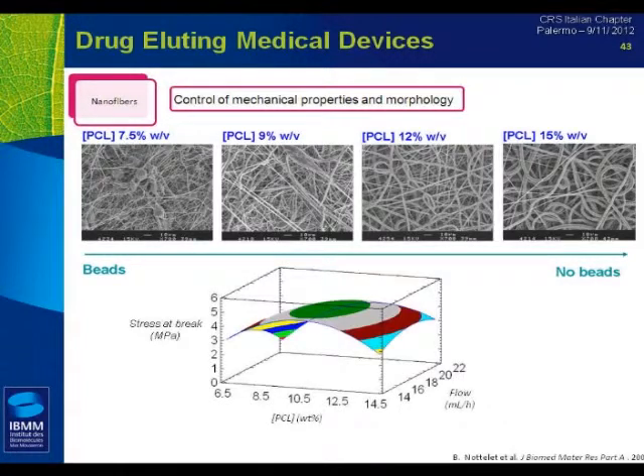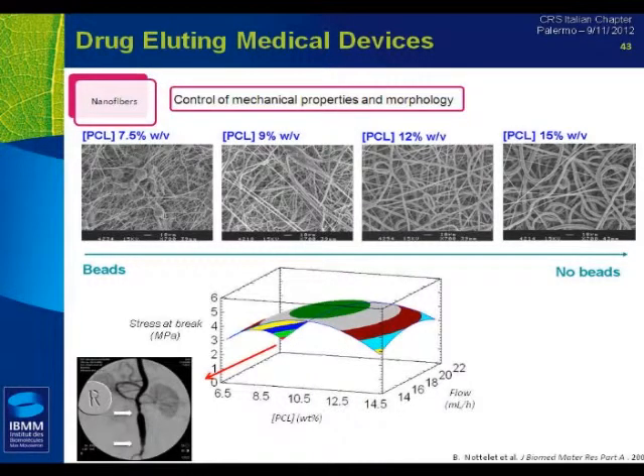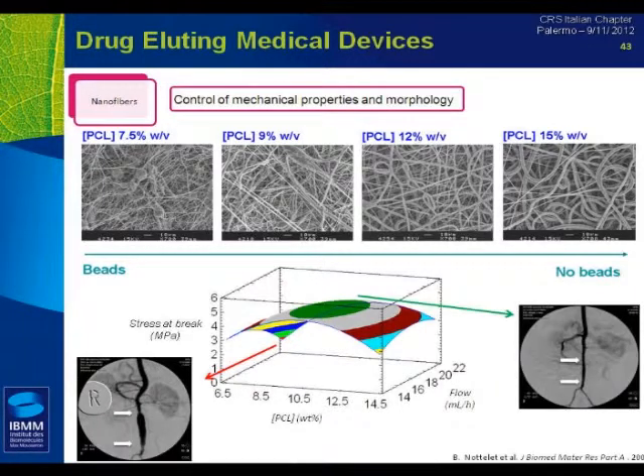You've got here an example of optimization. We look at the stress at break that can bear the graft. If we use a non-optimized graft, here the red dot on the left corner, you've got after implantation an aneurysm that appears, so the rat is dead. But then, of course, if you optimize properly your mechanical properties, you have this kind of angiography. You can see here the prosthesis is between the 2 arrows, the white arrows, and we don't see anything. There is no problem of aneurysm after implantation.